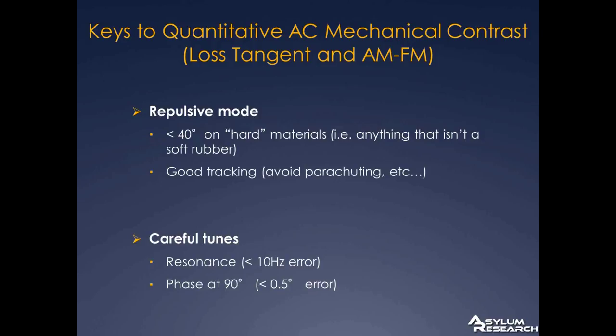I mean, what we've done here is we've traded one kind of calibration for another. If you want to do a force curve, and you want that force curve to be quantitative, you need to very carefully calibrate the optical lever sensitivity. You have to be able to convert the volts of the detector into nanometers of deflection. In this case, for both of these techniques, we don't have to do that.